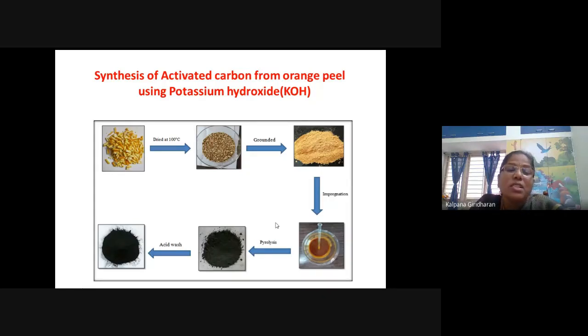We ate all the oranges, washed the peels routinely, dried them, and cut them into small pieces. My student is very smart and sincere - she cut the pieces into a very scalable, uniform unit, dried it at 100 degrees Celsius, and ground it properly with uniform size. She put it into a mixture where even the RPM was carefully controlled. Then we impregnated it with KOH, pyrolyzed it, washed with acid, and finally got activated carbon.